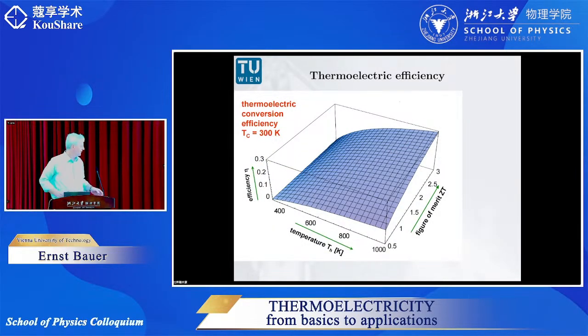So this is summarized here in this diagram, where the efficiency is indicated here on the z-axis. Here's the temperature, and here's the figure of merit. So if we consider everything with respect to room temperature, for example, and if we would have a couple of 100 centigrade temperature difference, and if we do have a very good material, say with a figure of merit of 3, then you can see such a thermoelectric conversion would have an efficiency of about 0.3. So we are far away from an efficiency of 1. And unfortunately, nowadays materials have in the best cases an efficiency of about 0.1.